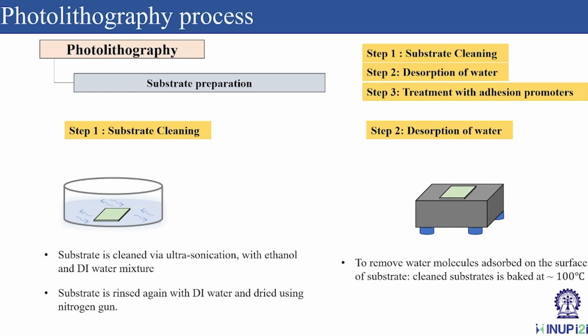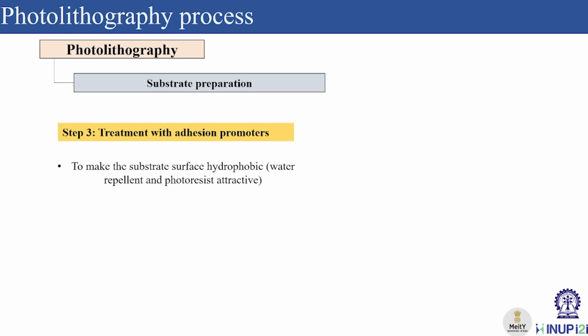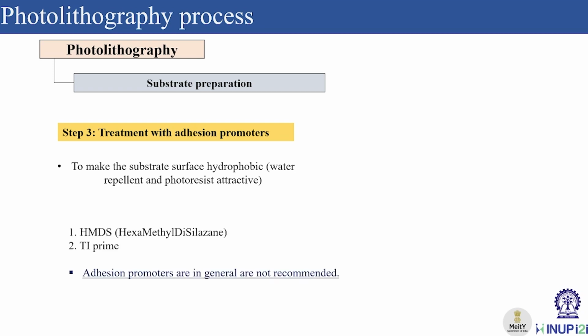Next, in order to remove the water adsorbed on the surface of the substrate, it needs to be heated. Generally we heat it at around 100 degrees Celsius for a few minutes. The next step is treatment with adhesion promoters. While we are treating our substrate with ethanol and DI water, the surface can become hydrophilic. But if our photoresist is hydrophobic, the layer will not be formed uniformly. Then we need adhesion promoters, for example, HMDS and TI prime.